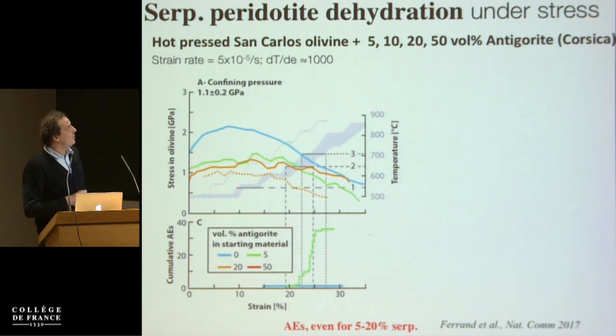And this is the stress-strain curve obtained for samples at 1 GPa, where this is the stress measured in olivine as a function of strain. And you see if you have pure olivine, it's very hard. And then as you increase the temperature, which is this gray hatched line here, you see some temperature softening. Now you put 5%, 10 or 20%, 5% or 20% serpentine, you see that it's already much weaker.